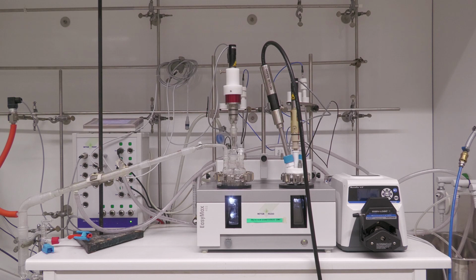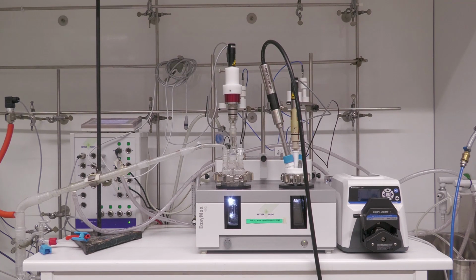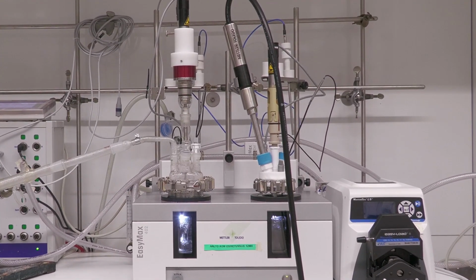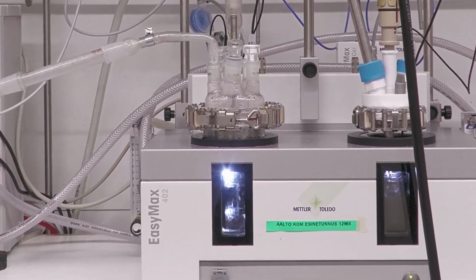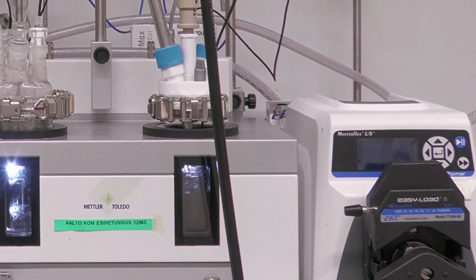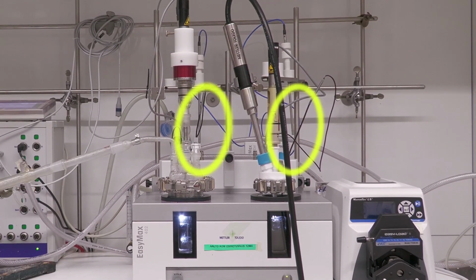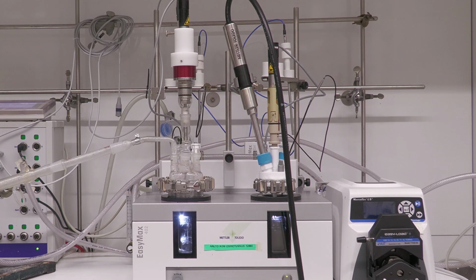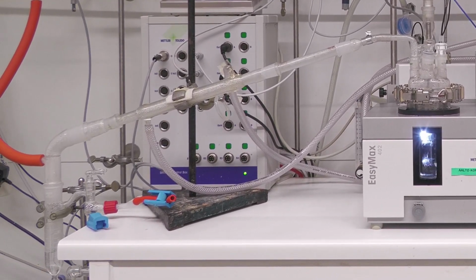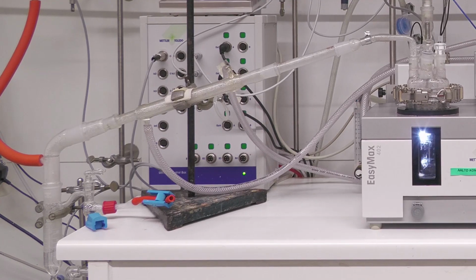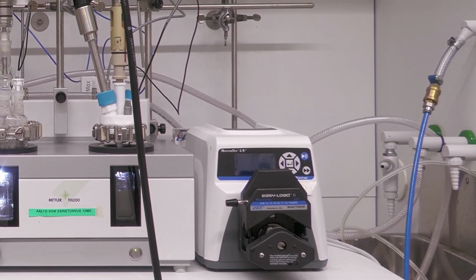A systematic study of the effect of crystallization parameters was accomplished in an EasyMax 402 stirred reactor station by Mettler Toledo. The station has two reactors with different volumes, 400 milliliters and 100 milliliters. Temperature sensors immersed in the reactor help to maintain an accurate temperature, especially important in cooling crystallization. Cooling crystallization can be done in both reactors. In a larger reactor, evaporative crystallization can be carried out using a condenser vacuum pumping system connected to it. In addition, a peristaltic pump connected to a crystallization system allowed a continuous supply of an antisolvent required for antisolvent crystallization.